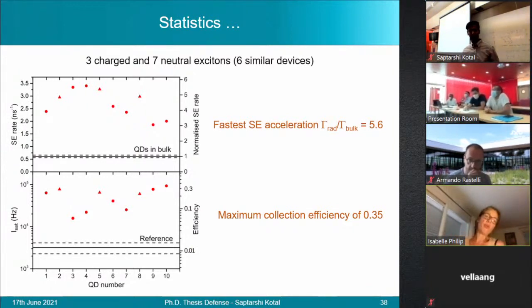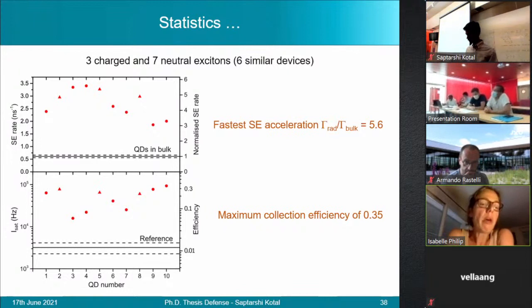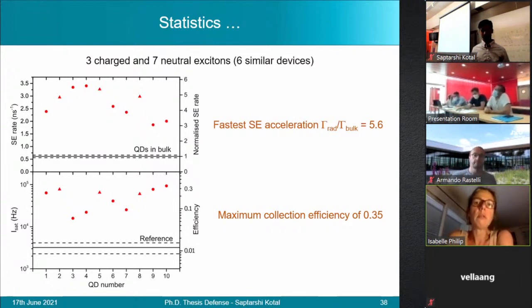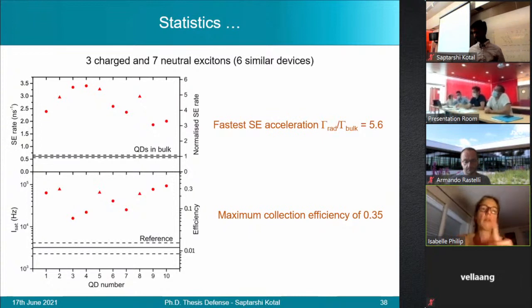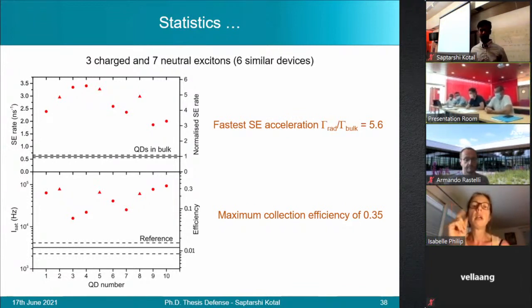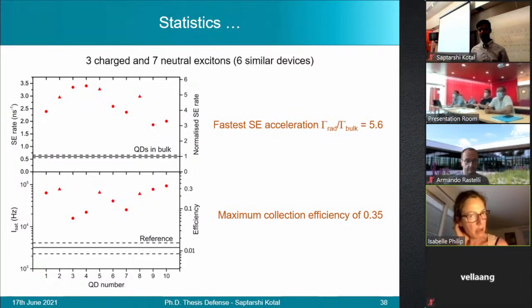And this brings me to another question, because when you are in bulk, it should be rather constant from what I understand. But if you go into the cavities, it will strongly depend on how the dot is positioned laterally. Because I think that when you are on the side, the lifetime and the collection efficiency shall be smaller than when you are on axis. Am I right? Yes. Okay, so this is why you see a stronger dispersion in terms of spontaneous emission rate and saturation intensity in the cavities compared to bulk. Do you think that this dispersion is related to dot position or something else?